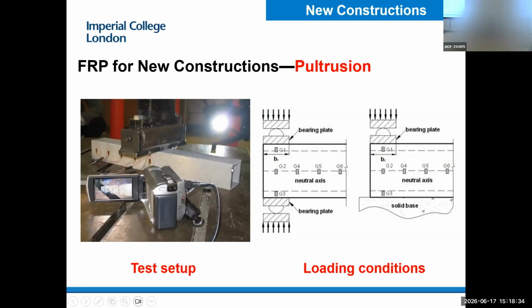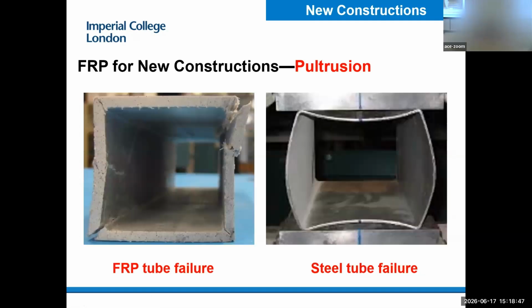For example, this is a square rectangular pultruded tube. I apply the load perpendicular to the transverse direction, with different loading locations and setups. The photo on the right is a metal tube, and this is an FRP tube. Both under transverse loading fail in completely different ways.